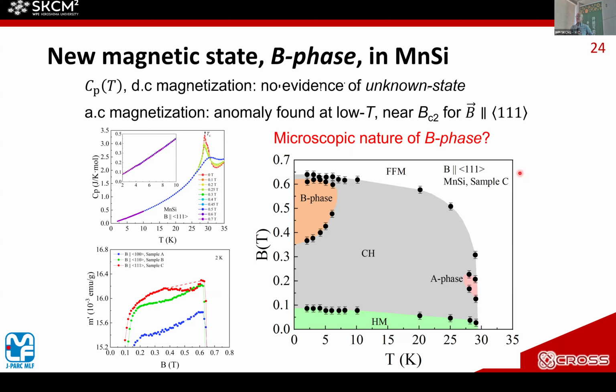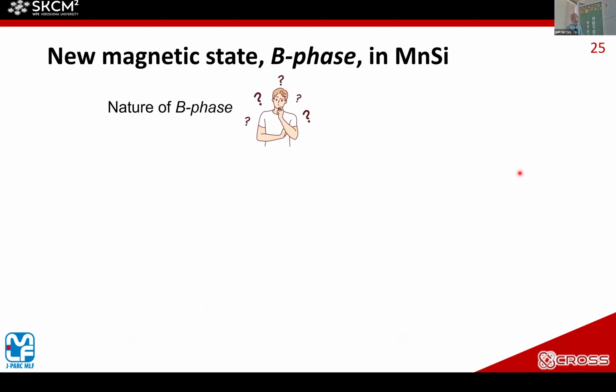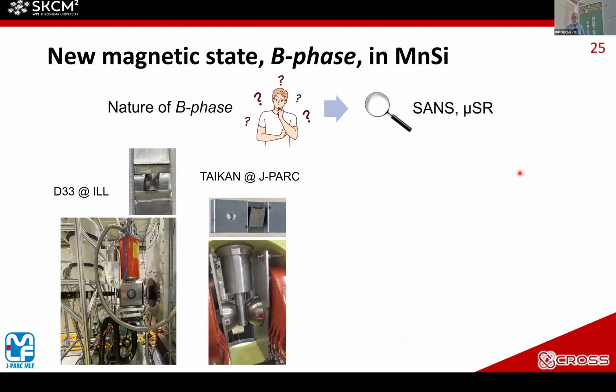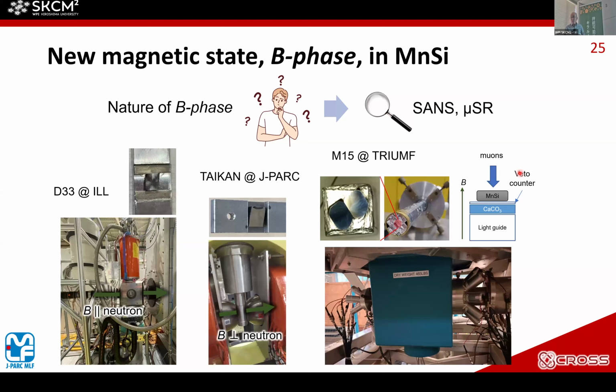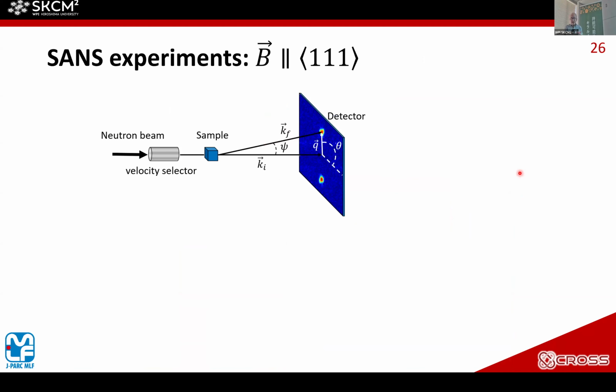Then, what is the microscopic nature of this phase? To understand the nature of the B phase, we have performed small angle neutron scattering and muon spin rotation measurements on MnSi. The small angle neutron scattering measurement was performed at ILL and J-PARC with these conditions. And also the muon measurement was performed at the Paul Scherrer Institute. Okay, then I will show you the neutron results first. The experimental condition is that the applied field is always parallel to the 1-1-1 direction. And the neutron measurement observes the diffraction which is transmitted through the sample like this.